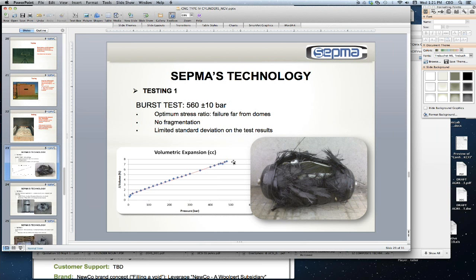So starting again from testing one, this is what the product looks like under catastrophic failure. You can see that the amount of debris is not contained. The fibers don't really go anywhere, and also the liner inside is not badly mangled, but rather it's failed through a single line.